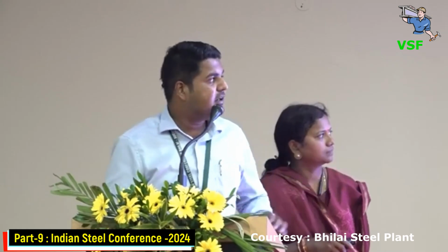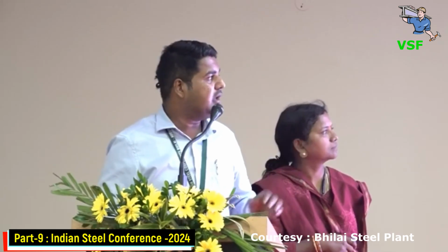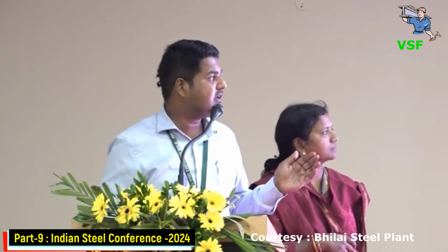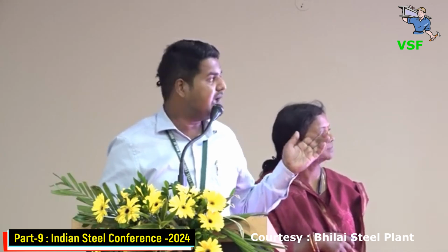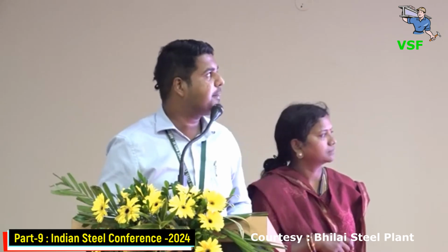So we have tested 3 gradations of each material, and we have defined what shakedown characteristics it follows at different load cycles. The results are, we have tested at 10,000 load cycles. The permanent deformation varies from 0.61% to 2.8%, and the gradations with better performance are HM2, G3, and the maximum permanent deformation came for SSG1. Similar results came. Next.